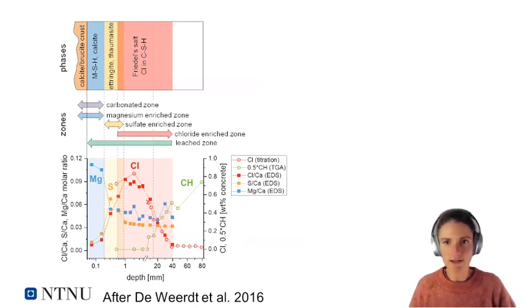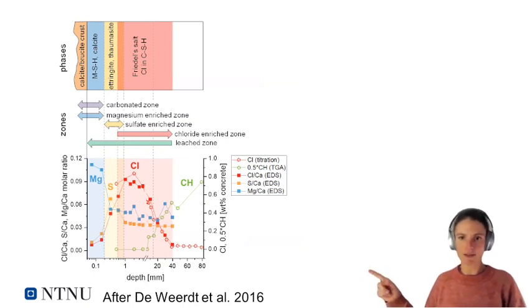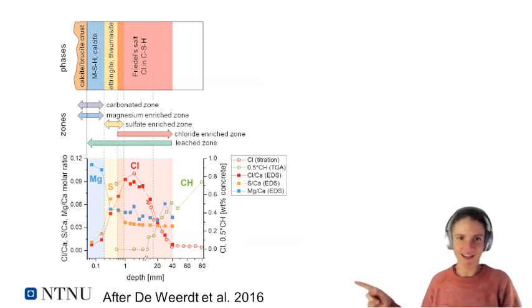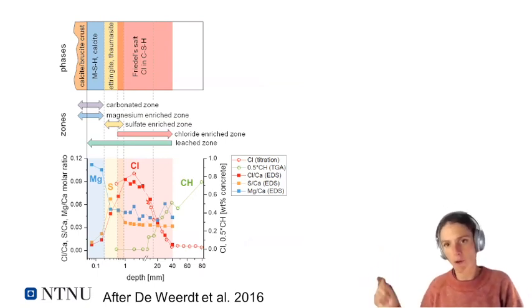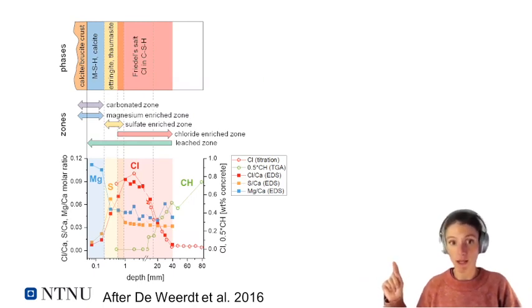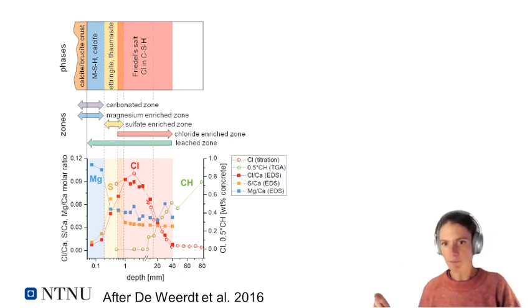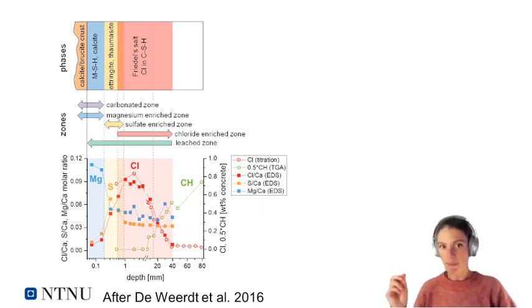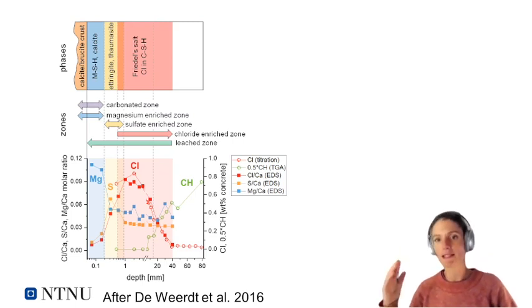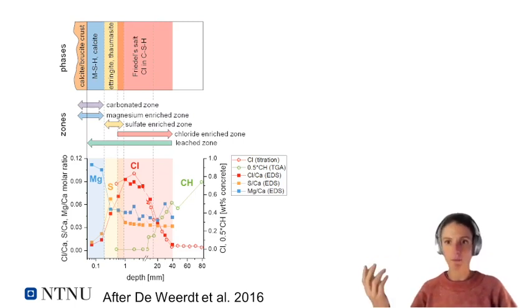And we see at the surface, the most left on this figure, we have this blue band where I've marked magnesium. So you can see that the blue curve is highest there. So we have a magnesium enrichment in that zone. And sulfur, which is marked with yellow, and chloride, which is marked with red, are really low in that zone. So at the surface, magnesium is high, sulfur and chloride are low. When we move slightly deeper in, we have a small sulfur peak. So we get a sulfur enrichment slightly deeper in. And then if we move even deeper in, we see that the red curve, the chloride curve, is going up, and we get the chloride enrichment.